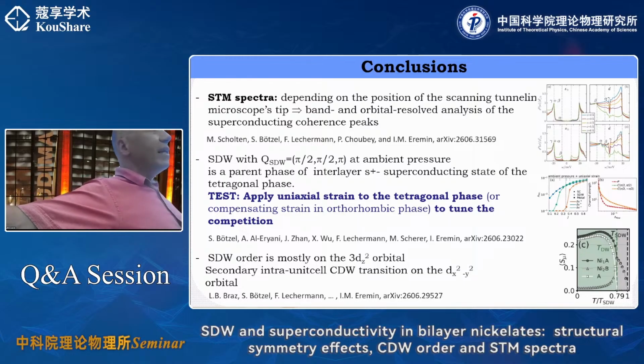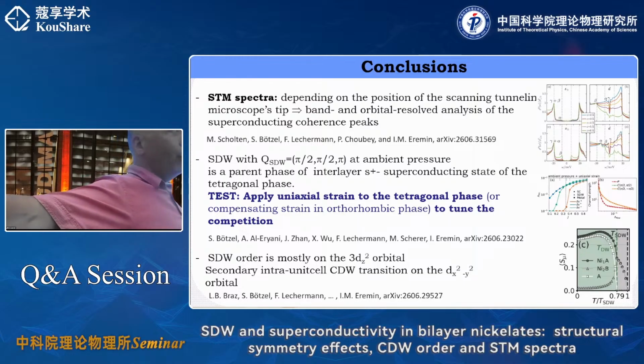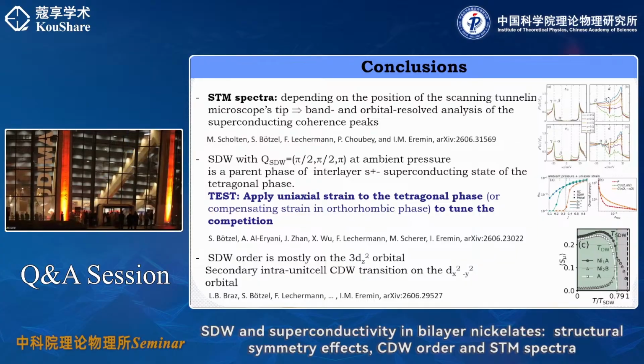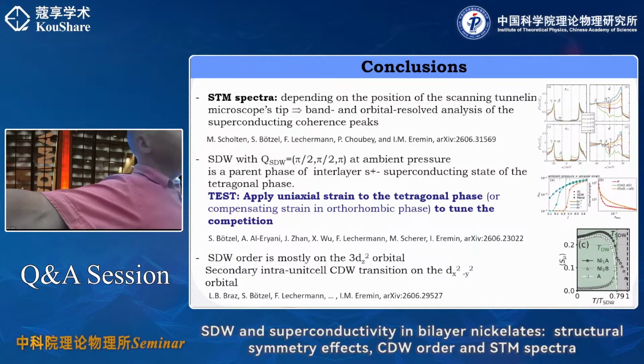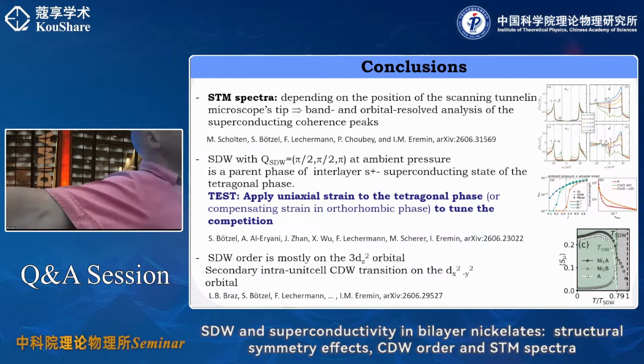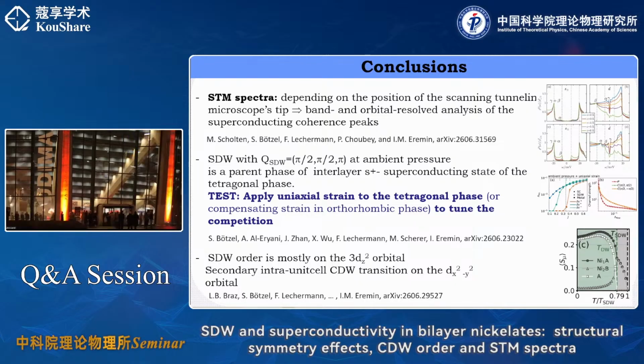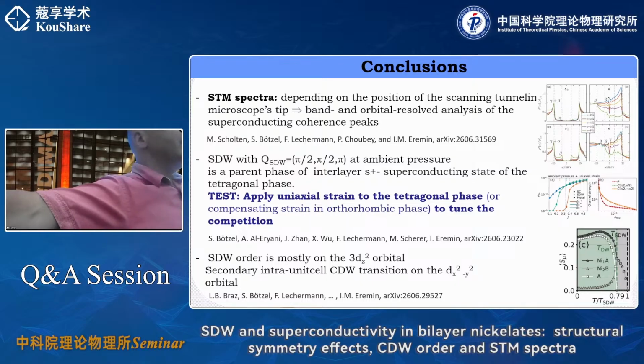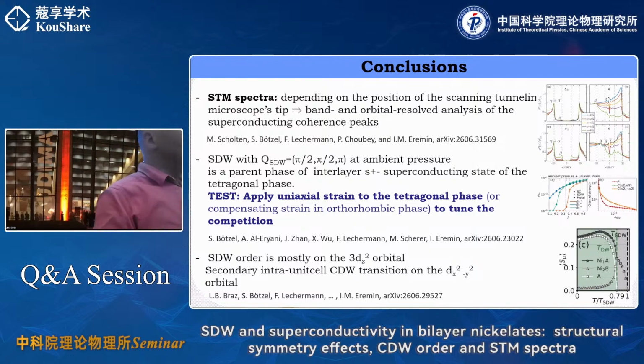However, I don't have an explanation for why they don't occur simultaneously. Within our theory, there is no guarantee that it occurs together, or it can occur at a lower temperature. In our case, we also see that we can tune them together, but then the transition becomes first order. And I think it is first order in the trilayer, right?